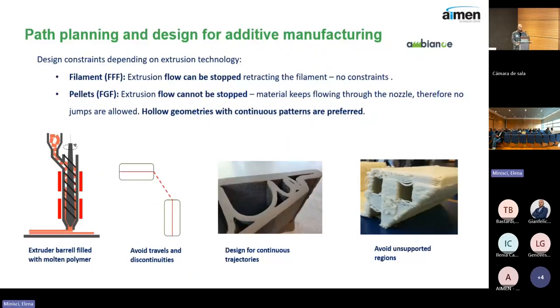Okay, so we can see now a bit more in detail these constraints regarding the technology. The main drivers of these constraints are that on filament, you can stop the flow very easily. You just pull up the filament and the polymer will not keep pouring through the nozzle. But on pellet extrusion, the molten material is inside a big cylinder. There's nothing to prevent it from oozing out the nozzle.